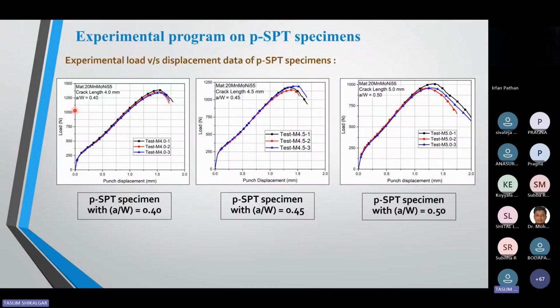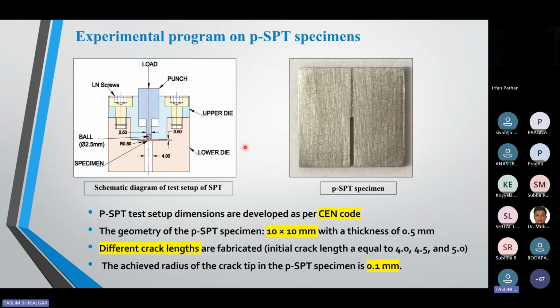I observed that my specimen is giving me the same behavior in each test. I tested this for 4 mm crack length, 4.5 mm crack length, and this is the 5 mm crack length. Because these specimen dimensions are very, very small, from these specimens I am only able to get this type of experimental data. And at most you can utilize this type of specimens for scanning electron microscopy. Beyond this, you cannot get more information. And if you want more information, like live, you need to use a camera or some additional methodology, because these types of specimens are kept in the die. So no one can observe how my specimen is deforming during the test. That is the major disadvantage.